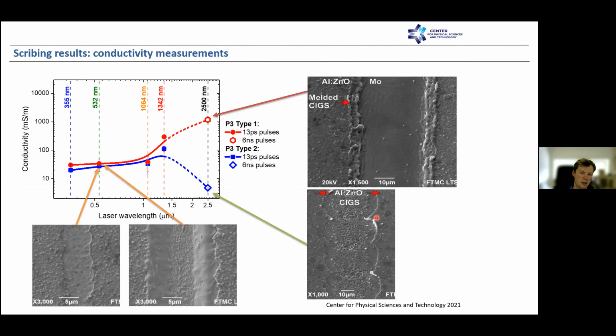With green, we see that the conductivity is actually quite low compared to other wavelengths. Of course, we have even slightly better results with UV for both P3 type 1 and type 2. If we go more toward infrared, we have an increase in the cell parallel resistance due to temperature accumulation inside the CIGS layer. With 1342 nanometer, for example, we have quite high conductivity values. Now, if we switch from the picosecond laser to the nanosecond laser operating at far infrared, P3 type 1 in this scenario gives a really conductive scribe.